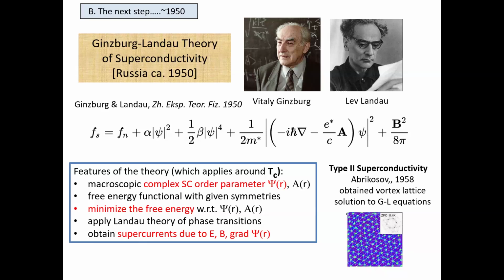And here is what Abrikosov explained with his theory, solutions to the Ginsburg-Landau equations, was that in type 2 superconductors, if you increase the magnetic field above a lower critical field, H sub C1, then you don't destroy the superconductivity. What happens is the magnetic field starts coming in through the surfaces here in vortices and forms hexagonal lattices. Hexagonal lattices like this. This one's not a perfect lattice because of defects, but what we have here is magnetic field lines coming through this 2-dimensional superconductor. All this purple is still superconducting.